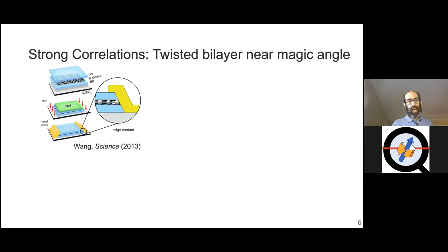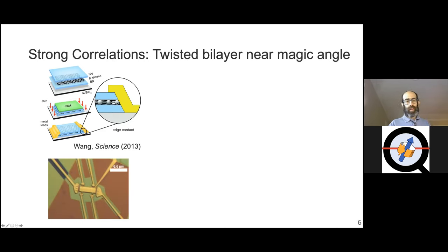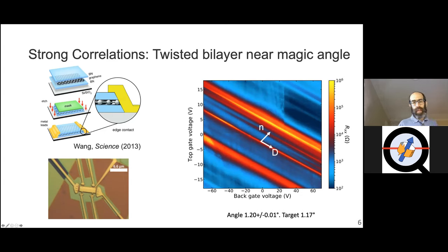I'm just going to say briefly how these samples are made. They're stacks of, they're not just two layers of graphene, but they're stacked between layers of boron nitride, which has typically been thought of as an inert, atomically flat dielectric. As we'll see, that's an oversimplified picture. And then through very clever work at Columbia from 2013, even though the twisted bilayer graphene is protected by these two layers of boron nitride, protected from the environment, one can still make electrical contact to it at the edge. And so here's an example of an image of a completed sample, in fact, the one that I'll talk about most. And the kinds of measurements that we can make often will be, for example, longitudinal resistance measurements.